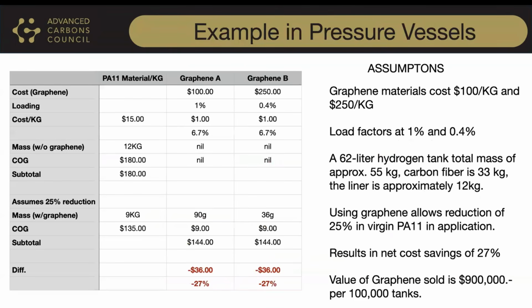Now we're going to use three different, very specific applications, and I'll walk through this briefly with you, and you can refer to it in the slides in more detail if you'd like. In this example, we're assuming that we're putting graphene into the liner of a pressure vessel, a type 4 hydrogen pressure vessel, which is a thermoset carbon fiber composite outside, but a thermoplastic liner inside. And in this 62-liter hydrogen tank with about 55 kilos total mass, the liner is about 12 kilos of that.